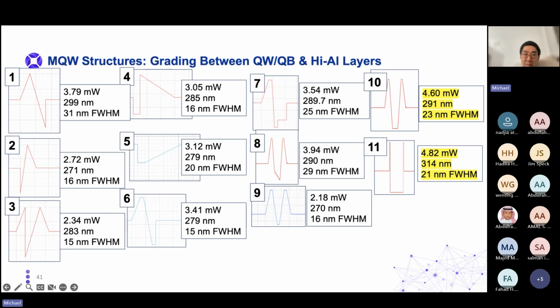So what I did was I tried a lot of different types of quantum well structures. You could look at this as the aluminum percentage around a quantum well. If you remember with the n-type smoothing layer, we had these pauses between the different layers of the n-type smoothing layer. We also had those pauses in the quantum well region. So those created these very thin high aluminum layers between our quantum wells and quantum barriers. So what I did was I tried to reproduce those with different structures and grading, from the quantum barrier grading up to that high aluminum, and then grading down to the quantum well, et cetera, et cetera.